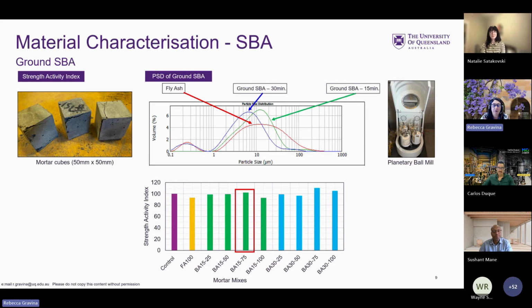And we found that the combination of stockpiled bottom ash at about 75% replacement of the fly ash in the mortar mix gave us an optimum amount that was close to our control, and also gave us a particle size distribution close to what you would expect with the fly ash as well, to try and control that performance. So there are ways that we can work with the SCMs to improve their reactivity in our mixes.